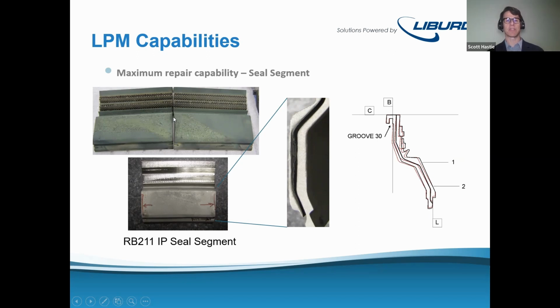You can see there's some missing material in between the seal here, and then if we look on this view, you can see that the seal has been opened up. Here's about the nominal thickness, and then over here it's been opened up where oxidation has taken away some of the material, where it oxidized and spalled and is no longer there or useful.